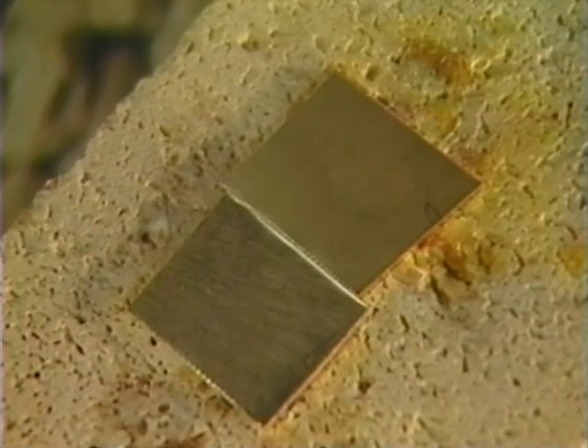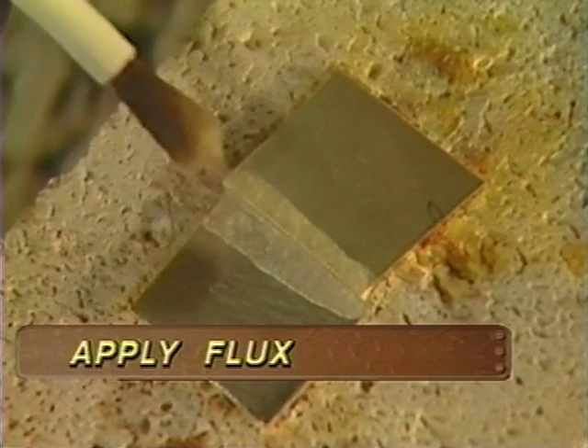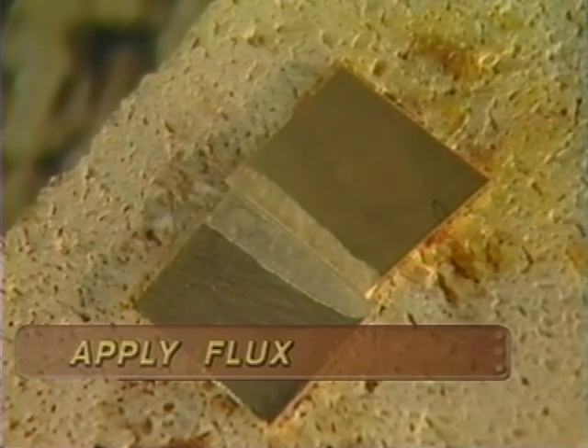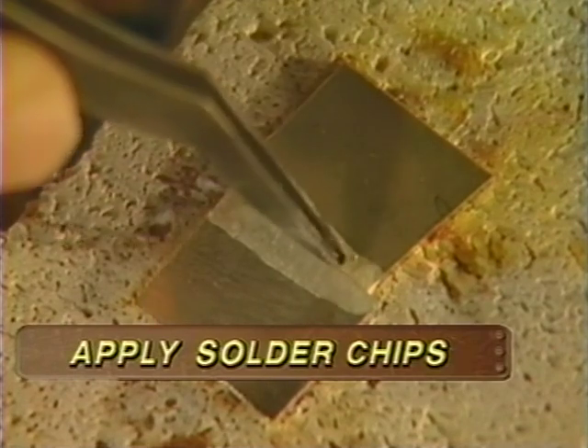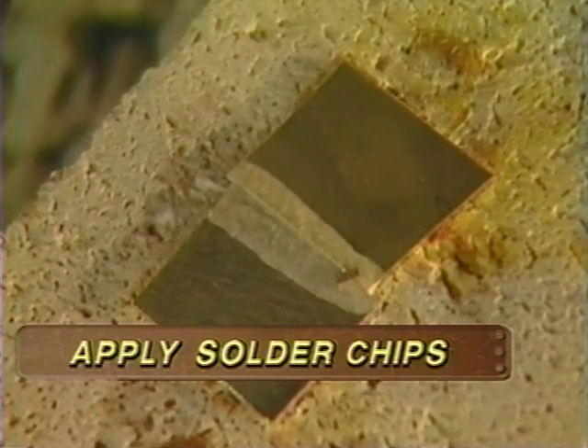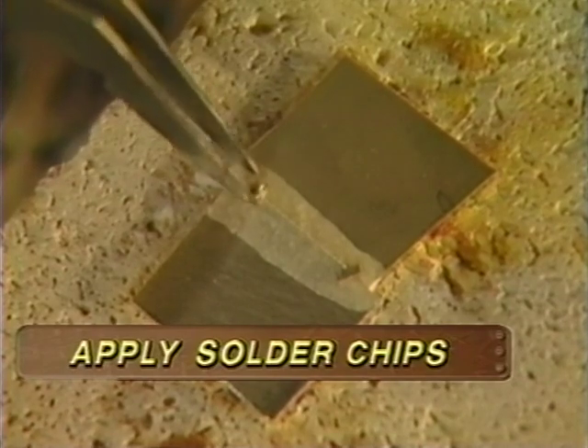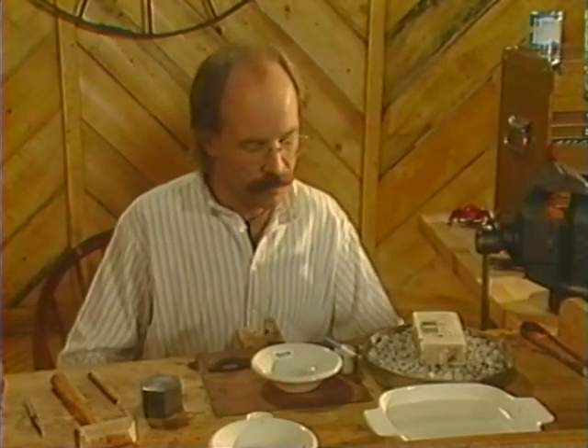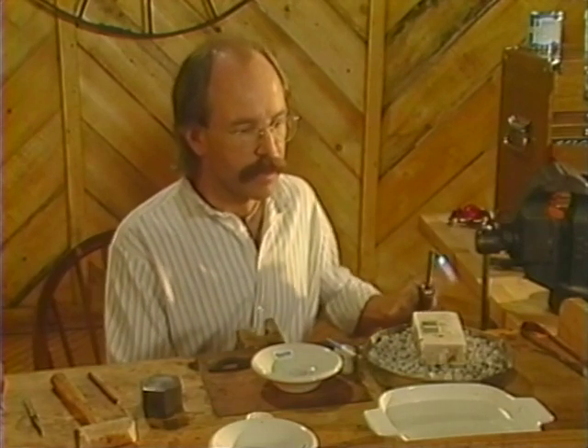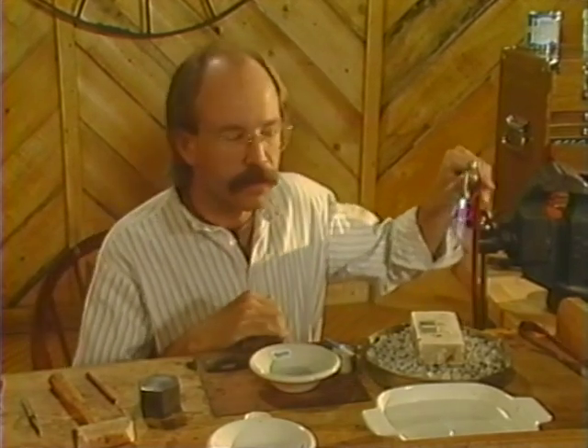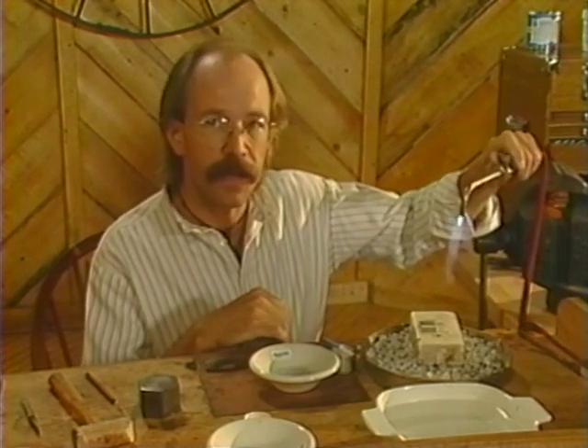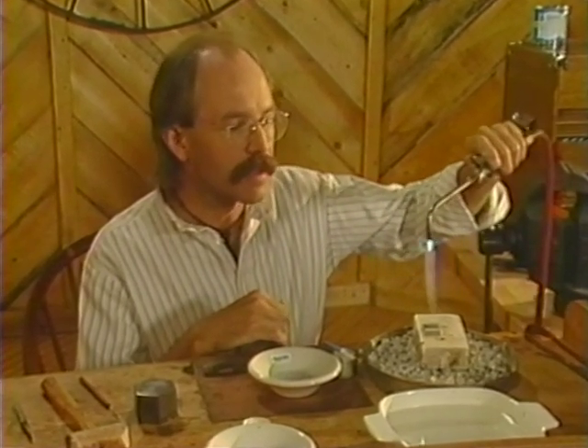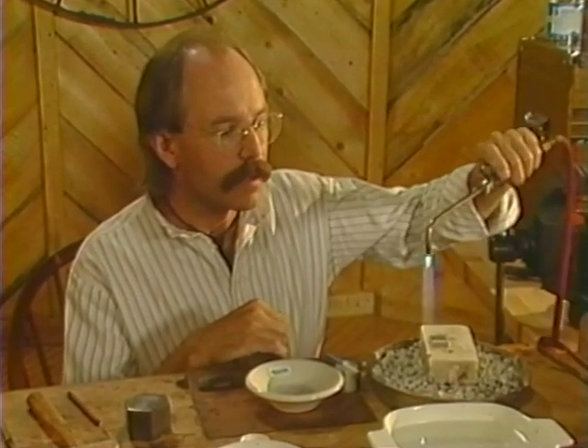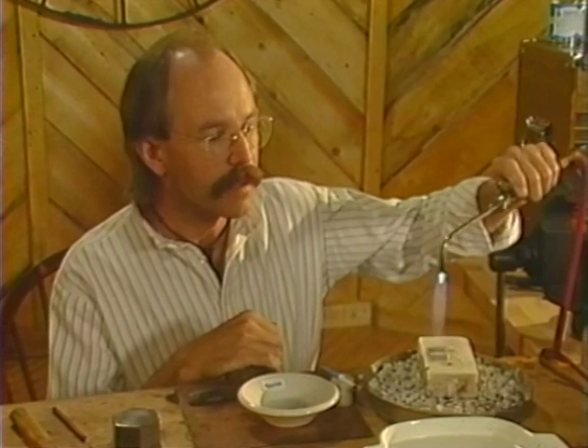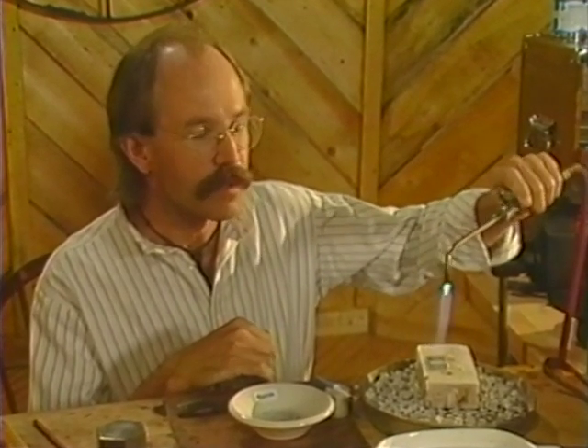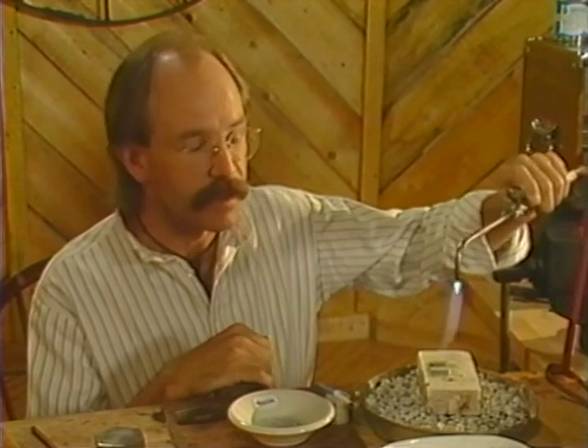Let's watch the process again. I'll apply flux and then lay the solder chips so that they span the joint. The flux uses water as a vehicle to create a consistency that can be brushed, and the first step is to evaporate that water away. You'll notice that I keep the torch well above the metal. If I come in too fast, too soon, the rapid boiling of the water will throw the solder chips away, and I'll have to reposition them.